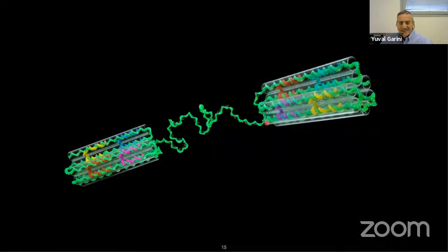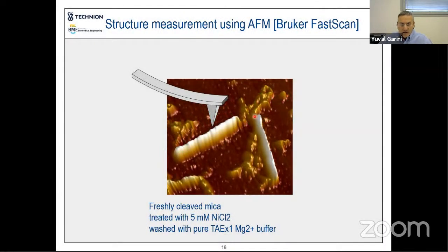And this is a more realistic scheme of the structure that we designed. You can see the two rods and the single-stranded DNA in between. And the purpose of the rods, the purpose of this structure, was to allow us to identify very clearly the two endpoints of the single-stranded DNA. Once you can measure the endpoint distance of the single-stranded DNA, you can estimate the persistence length. Okay, so in some way, the main purpose of the DNA origami was to identify those two endpoints in a completely clear manner. And we did that.